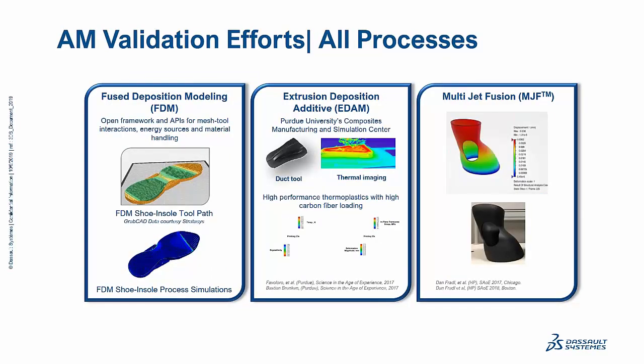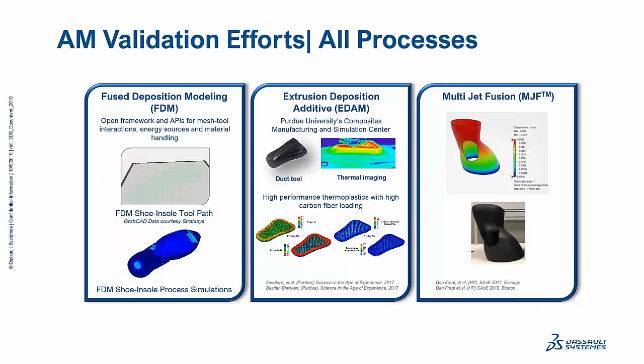Talking about different processes, here are some other examples of processes beyond metal powder bed simulations. What we're seeing here is a simulation of fused deposition modeling, this kind of shoe sole, and again we're activating the elements according to the path of the deposition tool that we have, and again this is a thermomechanical process, so we take into account that the material solidifies, maybe changes its properties during this process while this shoe sole is being printed. At Purdue University, they did a very interesting simulation of a fiber reinforced structure. And again, this was done with our simulation tools to simulate the printing of this duct tool. In this thermomechanical process, the thermoplastic material was being deposited and allowed to cure, and we're looking at the mechanical properties and things like crystallization over time, temperature management, and even things like fiber orientation, which is dictated by the print process and can be taken into account at this point.